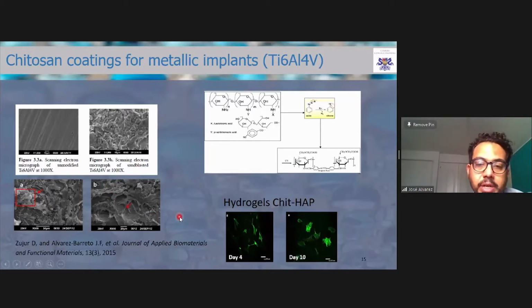Now, in this case, we didn't create a hydrogel directly, but we used a hydrogel-like coating for metallic implants, especially titanium, a titanium alloy, which is the most widely used alloy for metallic implants. And we created these coatings on these titanium implants, and we encapsulated a very important protein that induces differentiation of stem cells into bone cells, what we call osteoblasts. And we cultivated these mesenchymal stem cells, cells from bone marrow, and they underwent differentiation that we could see through different markers. One of the most obvious ones here is the formation of these calcium deposits that we characterized and confirmed were calcium deposits.